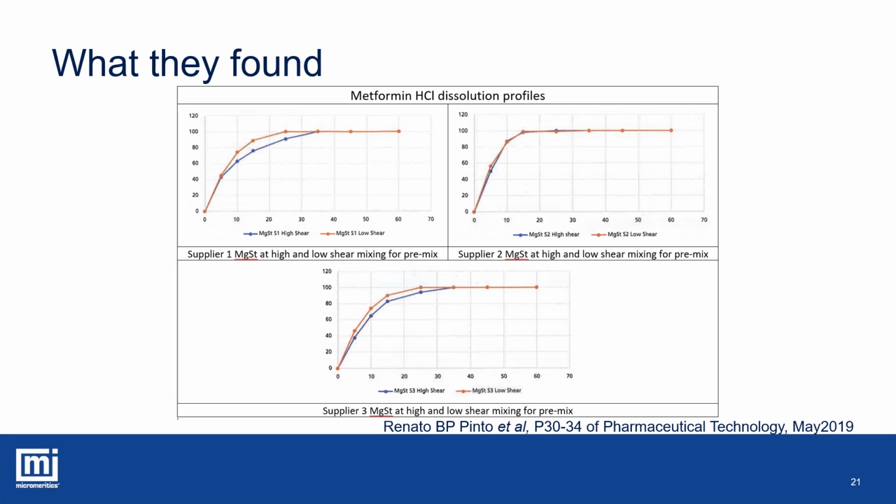So freeing these plates to their unagglomerated states would make the surface area higher and probably pretty much identical for these two samples. Looking at the data, I think mag stearate 2, if isolated in the same way, would be virtually the same as before the premix, because its blocky form can't deagglomerate in the same way.